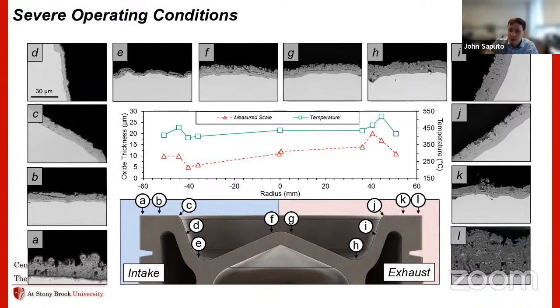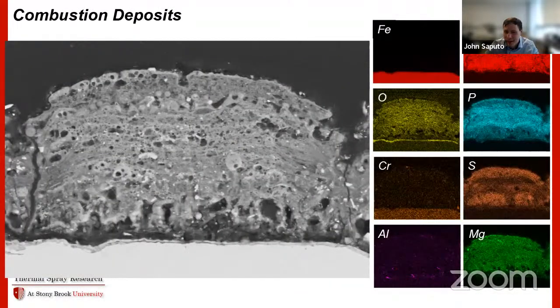So I'm showing temperature results from that thermocouple instrumented piston. You can see that pushes up to maybe a maximum of about 520 degrees on the exhaust side. And I'm showing the oxide scale that develops across each location. Some of these locations look kind of terrible. There's two specific ones that I'll go into detail here, L and J. Start with L because it looks the worst. But it turns out L isn't actually oxidation.